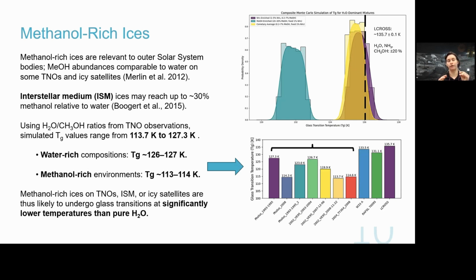But that was for water-rich ices. So again, cometary averages. But those aren't the only ices that we're potentially interested in. If we start letting the methanol composition increase to be more representative of high abundances found in the interstellar medium or even trans-Neptunian objects with some inferences of composition, then we see that the glass transition overall can get pushed to significantly lower temperatures, maybe 126 to 127 Kelvin for the more water-enriched, or if methanol is getting close to parity, even 113 to 114 Kelvin.